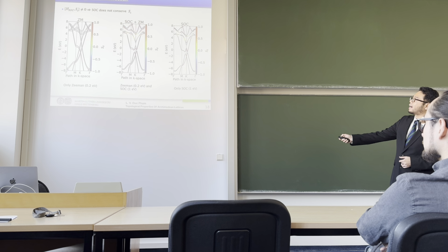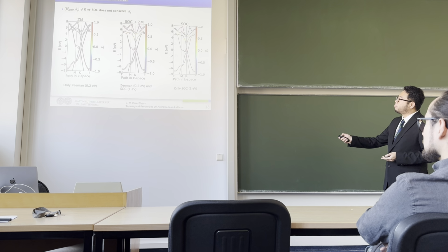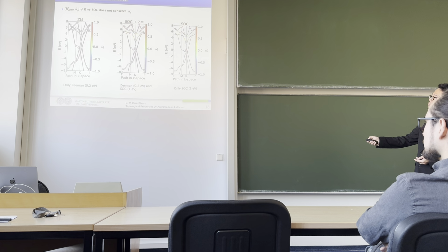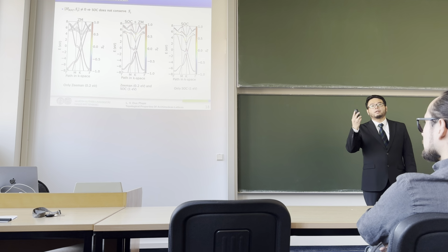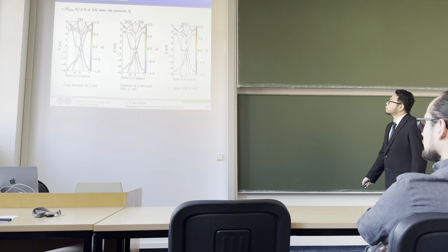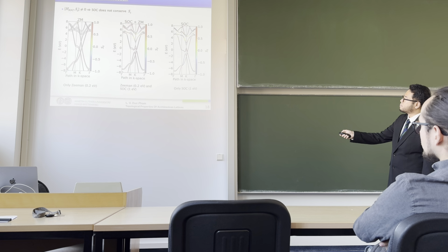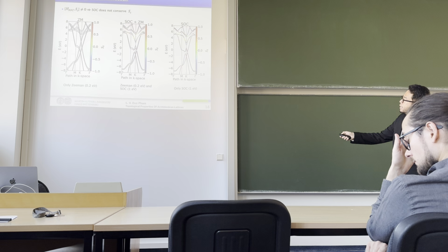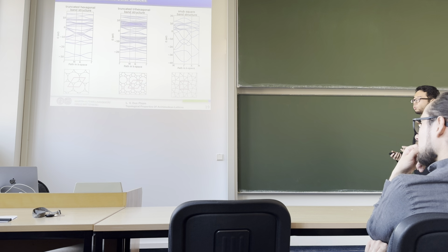And Sz in this case is either 1 or -1, so perfectly spin up or perfectly spin down. But if I add the spin-orbit coupling into this calculation, you can see just from the color that the spin, Sz, can now take values between 1 and -1, and in some region you even see that the color turns to green, which means Sz is almost equal to 0, and which means the spin is turning into the two-dimensional plane. And here, lastly, is the calculation with only the spin-orbit coupling, and you can see that the spin mixing effect is still very dominant over here, and it also splits the bands of spin up and spin down along the pathway near gamma.